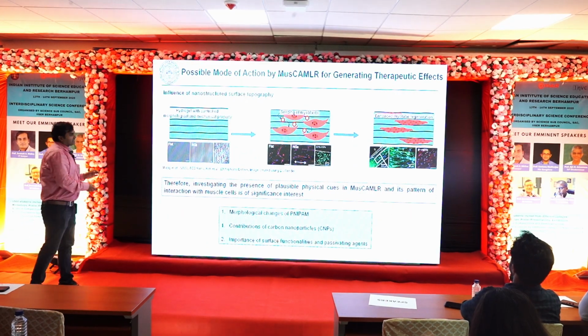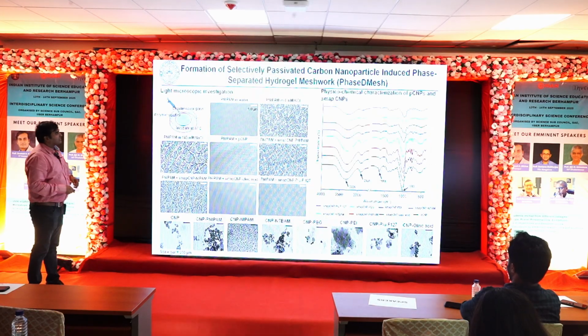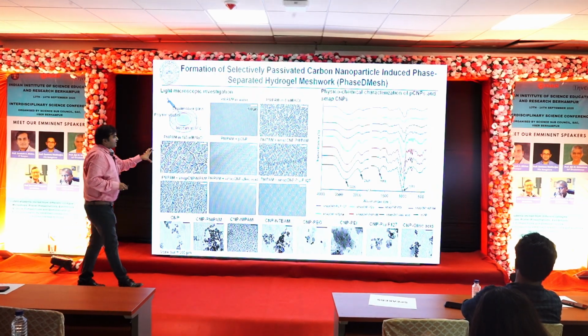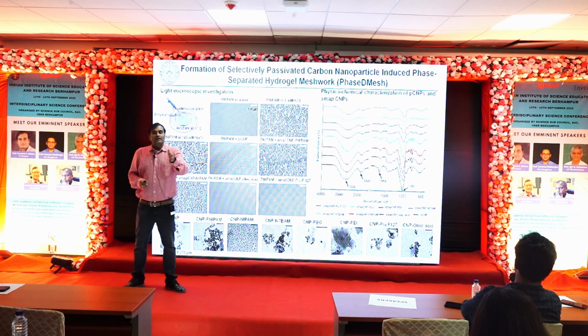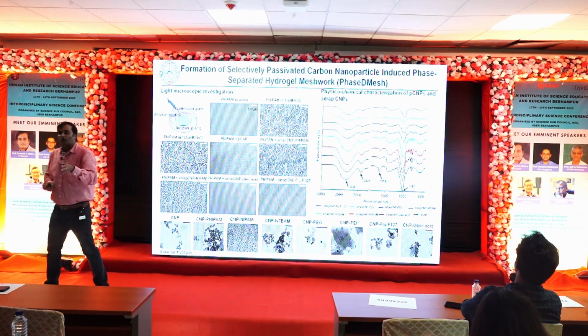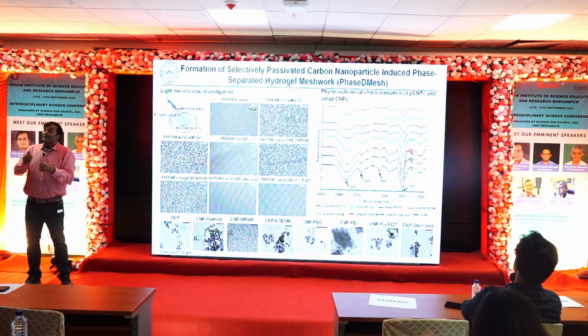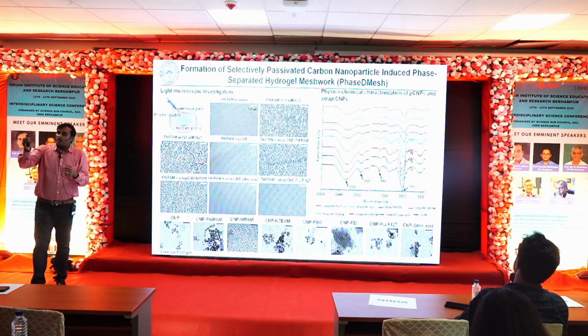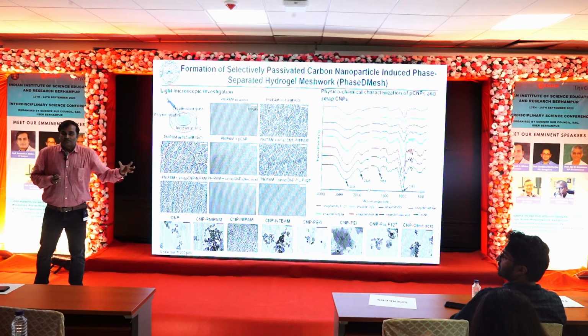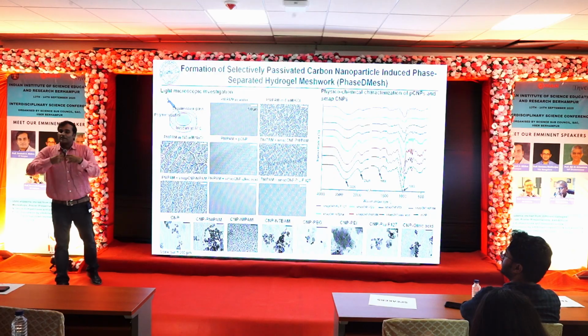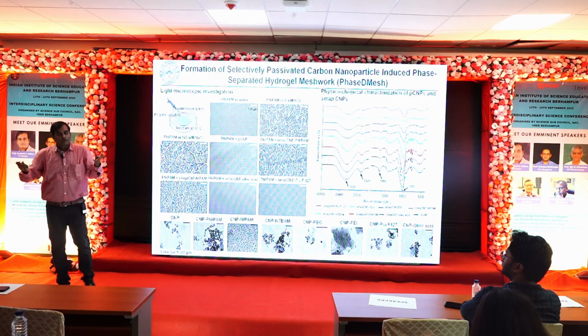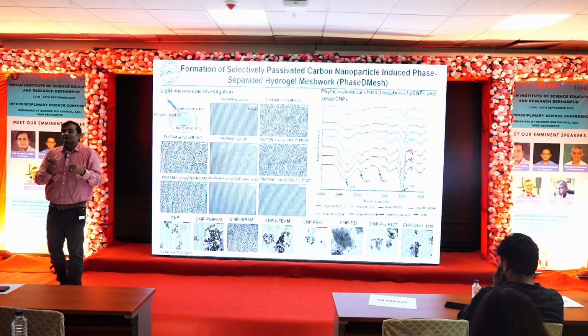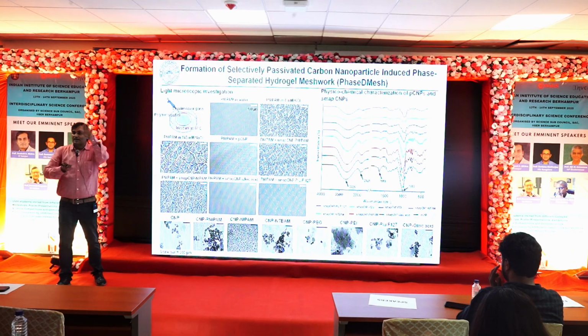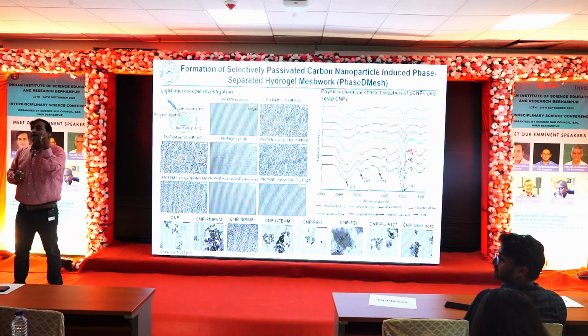So for that we designed a new set of experiments. Then we tried to see what actually influences the focal adhesion, and we found that extracellular salt content influences it, right? If there is a lot of salt present in the extracellular space, that can influence the way cells will attach to the surface. So we tried to manipulate it.